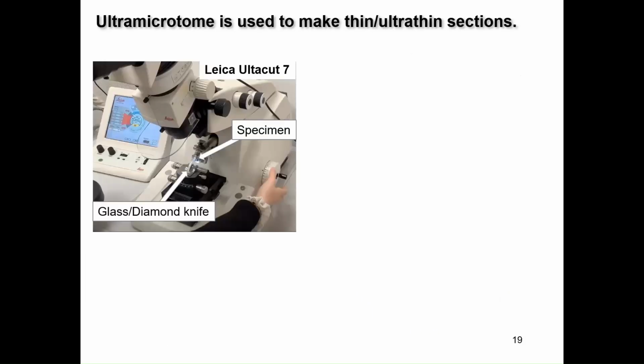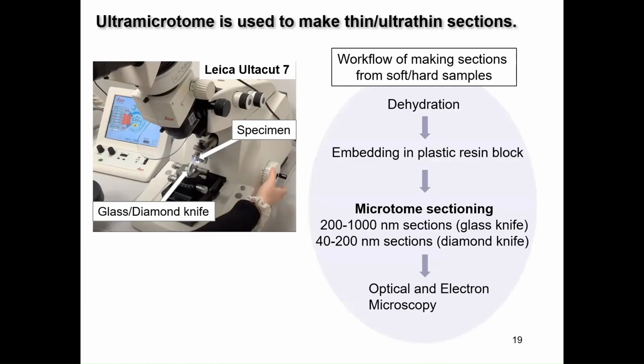Another sectioning tool is ultramicrotome. We have Leica UltraCut 7. So here is the specimen block, and here we have a glass knife in this photo. And we can cut both soft and hard samples, and we use a glass knife or diamond knife. If the samples are wet, we have to dehydrate them because we want to embed them in a plastic resin block, and plastic resin doesn't polymerise if there's water content. So they have to be dry, no water, before embedding in the plastic resin.